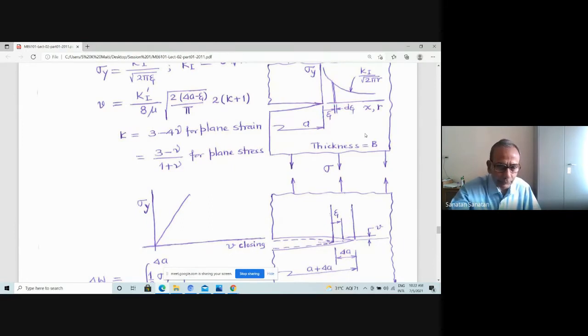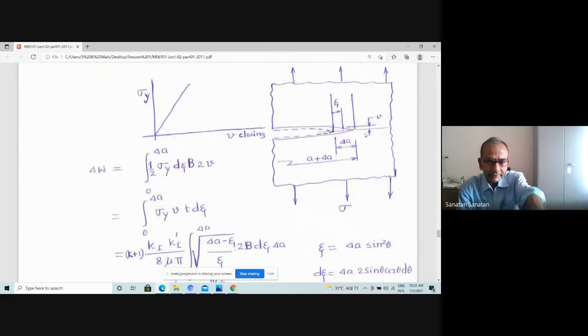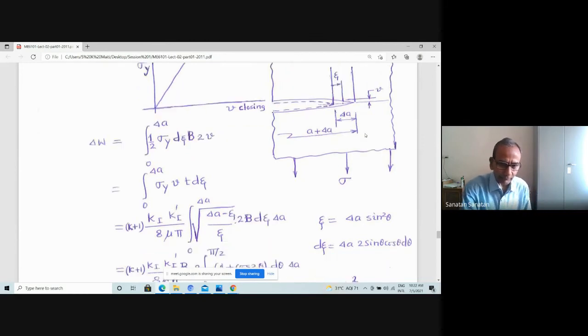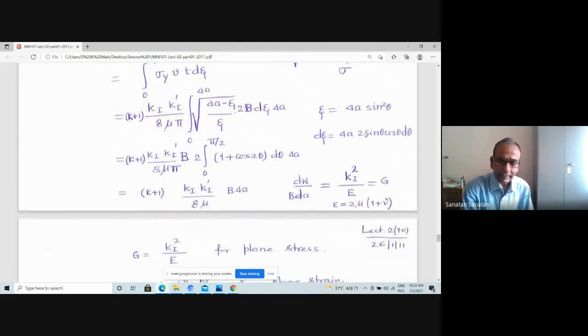I have to make that 2V 0, and therefore the work done in closing the crack is given by this. This is the energy which is required in closing the crack from A plus delta A to A. And all this calculation was done by using this solution. And finally, you see that this became, as delta A tends to 0, the energy that is required, the work done per unit crack extension, is given by K1 square by E. And that is nothing but the strain energy release rate of Griffith.